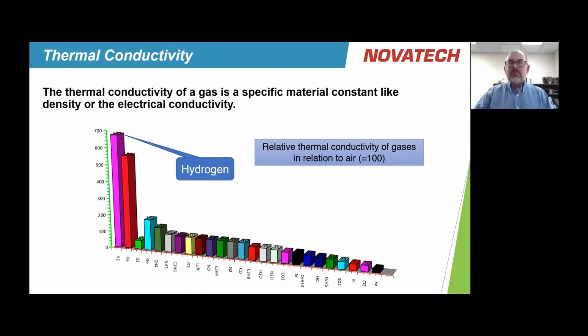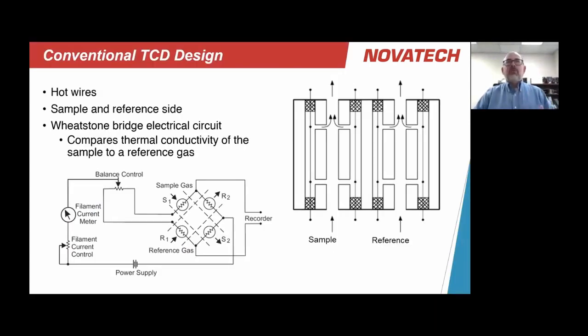And because it is so very different to everything else, we can look at the overall thermal conductivity of a gas. And if we have a good understanding of what it's made up of, and primarily if it's a binary mixture, two components only, we can use that thermal conductivity to approximate how much of it is hydrogen. And so that's the concept of how a thermal conductivity analyzer works. The way we measure the thermal conductivity is essentially we look at the gas's ability to conduct heat. So we have a sensor that's made up of hot wires. One side is exposed to the target gas, or the sample. The other side is exposed to a constantly flowing reference gas.